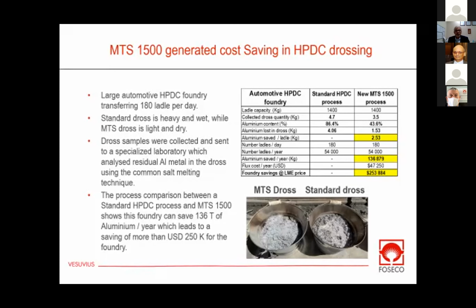So they did a number of processes with our MTS 1500 technology. We collected the dross, we averaged the value, and you can see there with our process, the overall dross quantity is around 3.5 kilo per ladle. We sent that sample to an outside lab, and the analysis came back 43% of aluminum is trapped. In other words, our MTS process is able to remove valuable aluminum from the dross before you remove the dross from the ladle. So this is a huge saving.